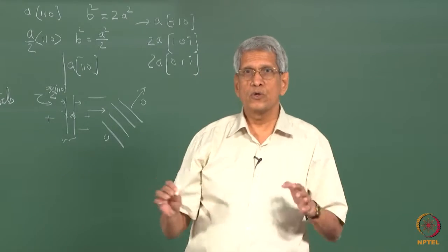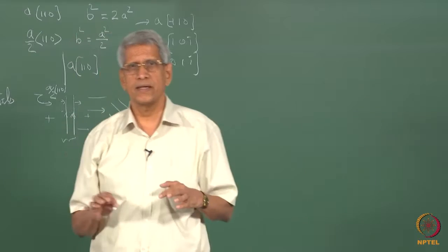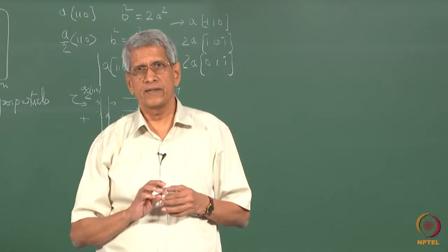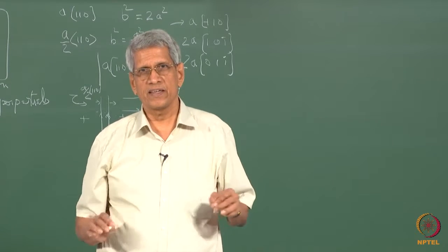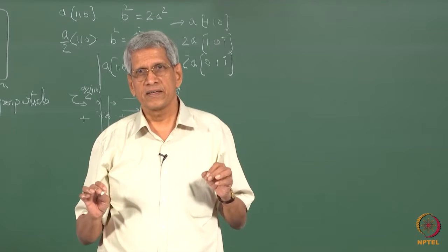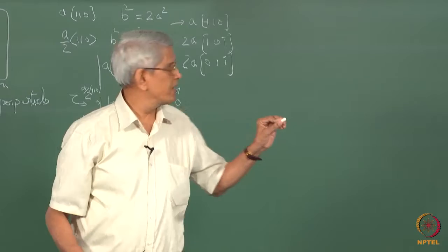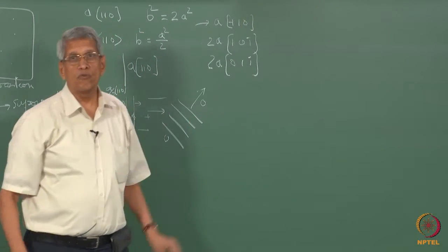Okay. So generally people say that whenever in any material we see pairs of dislocations, we say that ordering is there. That is not correct, because that depends upon the crystal structure. This is one example where in this direction 4 dislocations are needed.